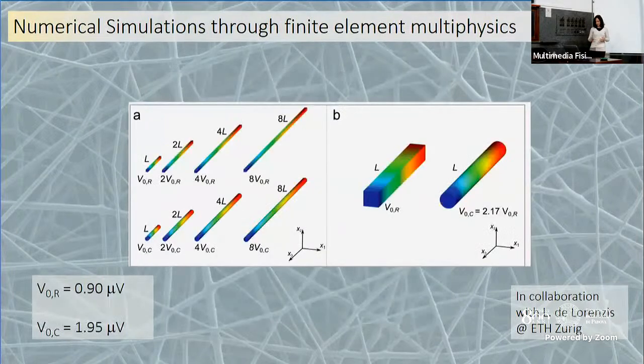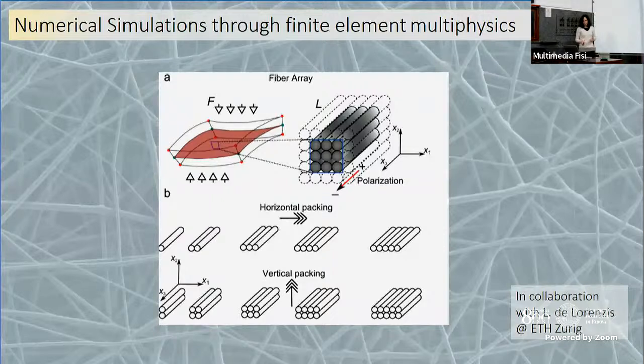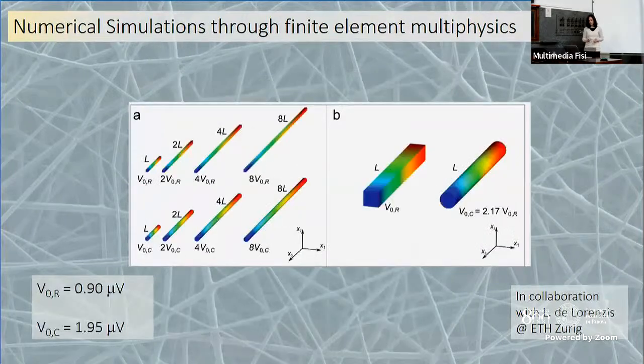And to answer this question, we studied two different packagings, a horizontal one and a vertical one, as you can see in the picture. The first result on isolated fiber tells us that the intensity of the polarization along the fiber depends on the length of the fiber. So we could save computational time by simulating very short fibers with respect to those we use in the experiment. The second interesting point was that the polarization depends on the shape of the cross-section.